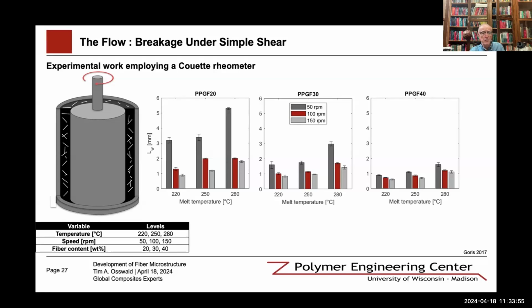In the Couette, we can control the temperature, so we can have different temperatures. Here we show 220, 250, and 280 degrees. We can see that lowering the temperature to 220, of course, gives a higher viscosity than 280, which leads to more damage. So at 50 RPM, you can see fiber length going from about 3 millimeters at 220 degrees to retaining about 5 millimeters at 280 degrees. So the effect of temperature can be assessed, and the effect of RPM.